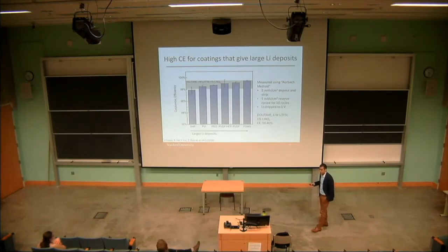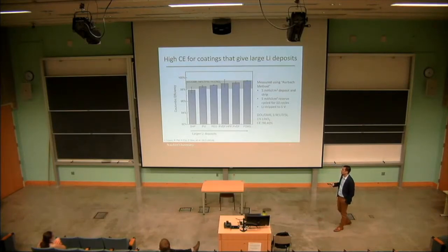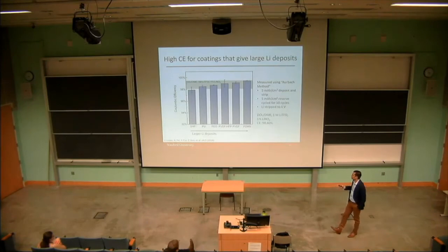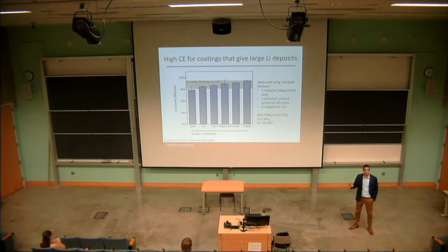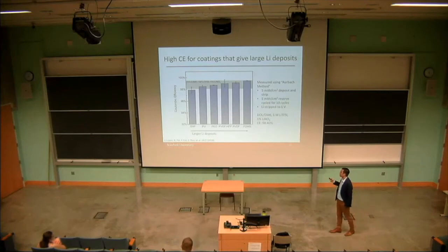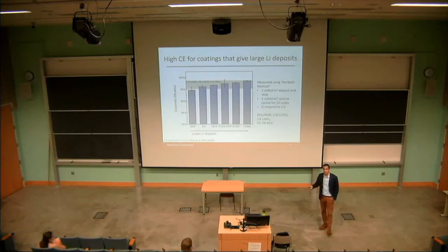When we look at the cycling efficiency, and again, this is just how much lithium you can remove after you deposit a fixed amount of lithium, we see that in general, the polymer coatings that give smaller lithium deposits have lower Coulombic efficiency, and the materials that have larger deposits give higher Coulombic efficiency. But unfortunately, this isn't a perfect relationship. Remember, PDMS was really in the middle, and then the fluoropolymers were the largest lithium sizes, and this is because there's also surface reactions that happen that are also very important that we're ignoring here by just looking at the thermodynamics of this process. However, we do have now two very easy to measure properties of these polymer materials that allow you to design new coatings moving forward.